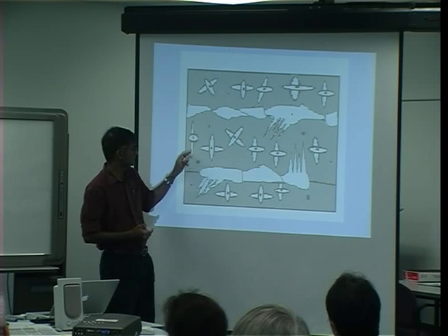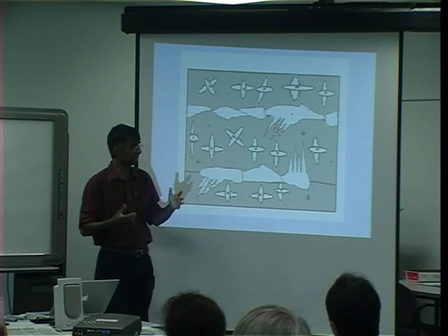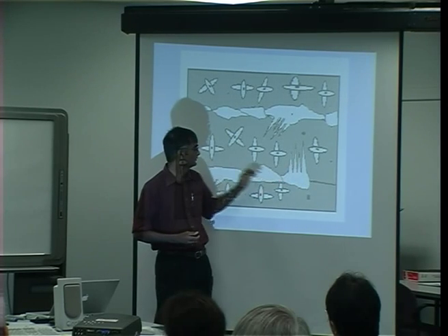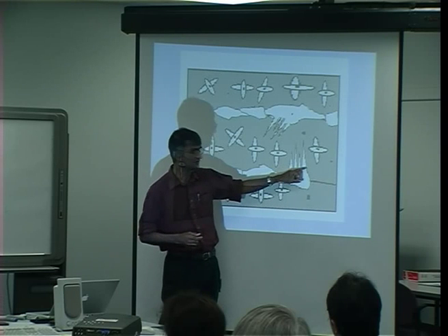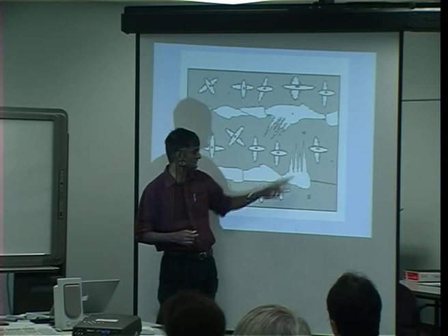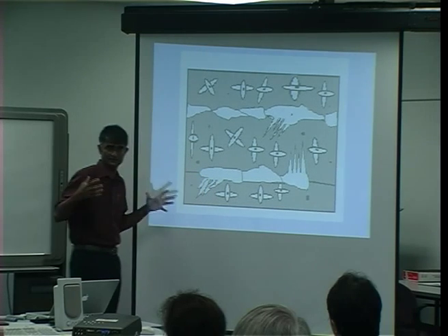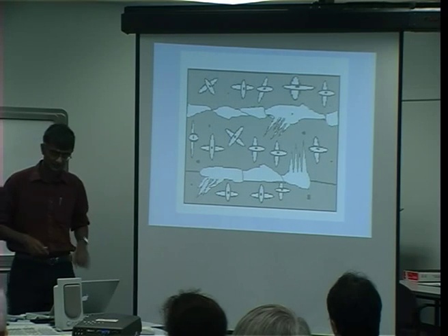And the reason is that, again, the plates point in many different directions as opposed to forming these packets. So a crack propagating across there is frequently deflected, whereas here it can basically grow across a set of packets or across one of these coarser grains. So acicular ferrite is the desired microstructure in welds.